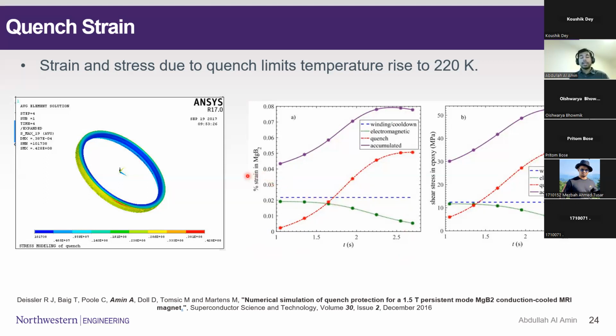In addition to the strain in the MgB2, there were other modes of failure, which is the shear in epoxy. There is an insulation layer which cannot take too much shear. I'm assuming that from your basic mechanical engineering or solid mechanics course, you are pretty well aware of what shear stress or strain is. In such a scenario, we also plotted the change in the shear stress in the epoxy, and we realized that it can withstand 50 megapascal. So if we use an epoxy, we better choose one that can withstand this amount of stress. In reality, Ohio State, with whom we were collaboratively doing this research work, were looking for an epoxy that can go beyond 150 megapascal by considering a safety factor of 3.